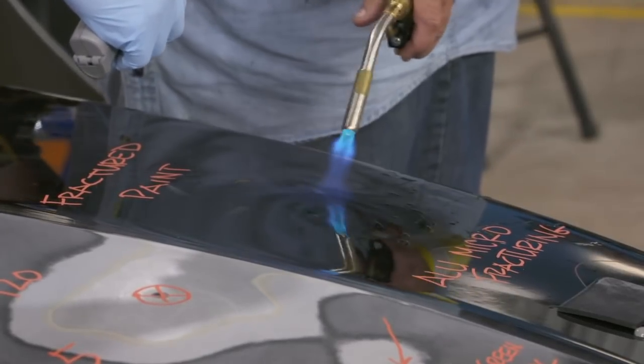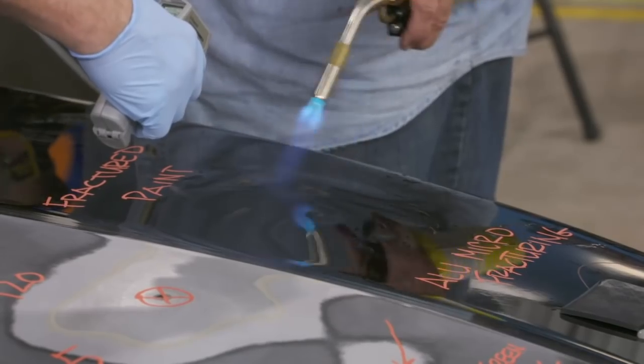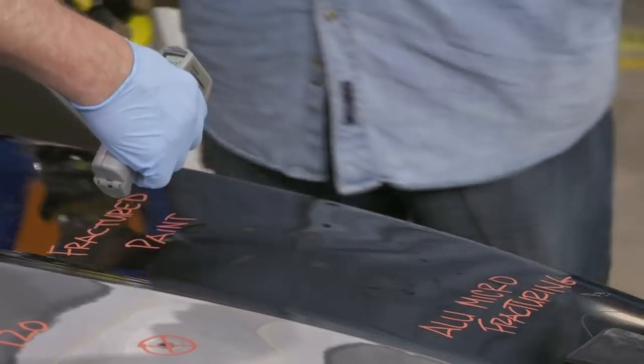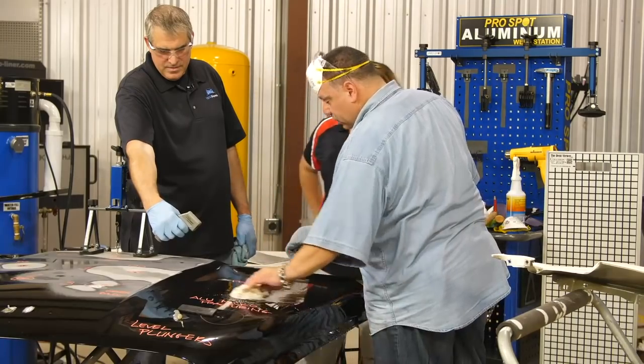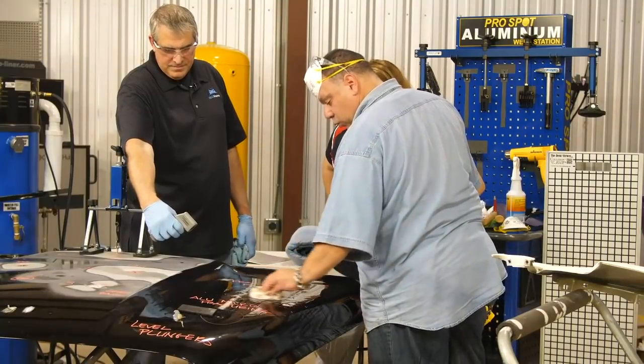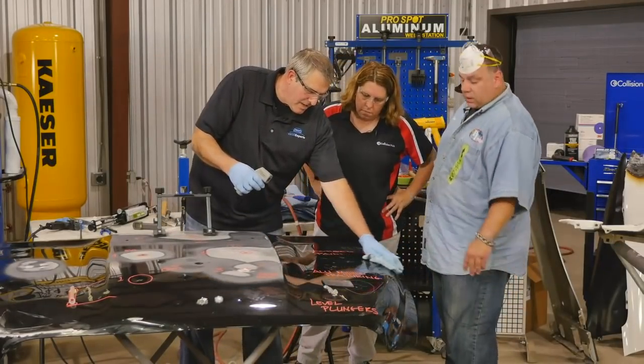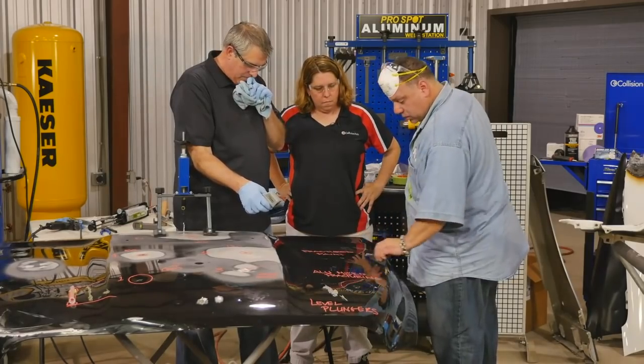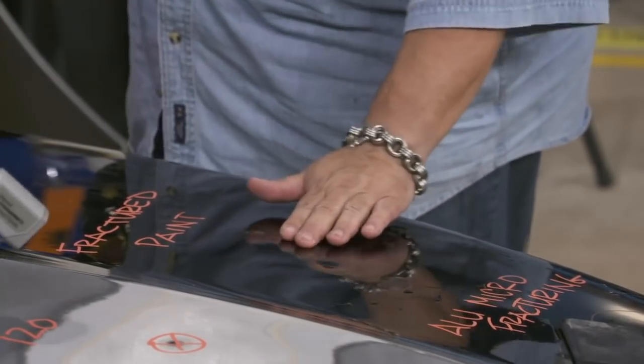We're at 420°F. It depends on how fast you move and how quickly you go around it. This rose up pretty high, and you can do this 50, 60, 3000 times if you had to. Obviously you're not going to do that because you can't use water to quick cool and you're not going to sit there and wait. You can see I've got the paint to crack. What's happening is the paint in that area has cracked because of the quick cool. Is the aluminum cracked underneath that? It possibly could be. You don't know unless you sand it down and check. I'm probably going to save this hood and the next time I come back in two months, I'll do some testing with it to find out what's there. But more of it's been removed.